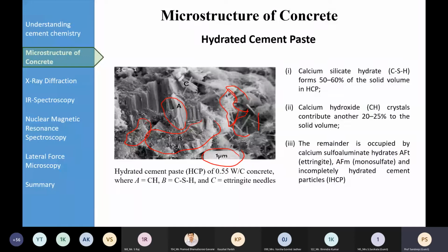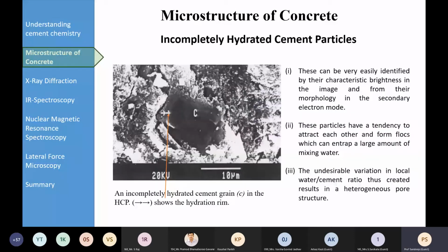So ideally, we should ensure that there are more and more of the calcium silicate hydrate structures in the microstructure, because this is the hydrated cement paste, and this gives a confidence also that yes, hydration has taken place completely for the cement paste. Now we can easily identify the incompletely hydrated cement particles also in this microstructure of the concrete. They can be easily identified by their characteristic brightness in the image. So you can see here there is a characteristic brightness in the image, and from their morphology in secondary electron mode, they also have a tendency to attract each other. And once they attract each other, they form flocks, and these flocks in turn can entrap a large amount of mixing water.